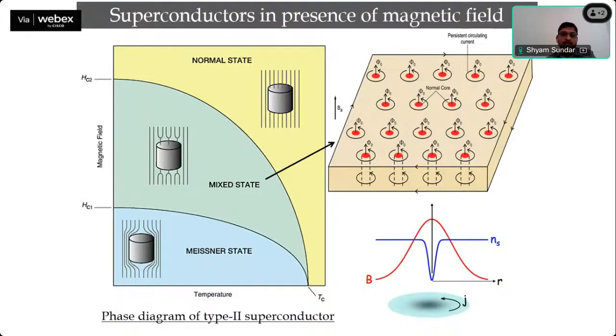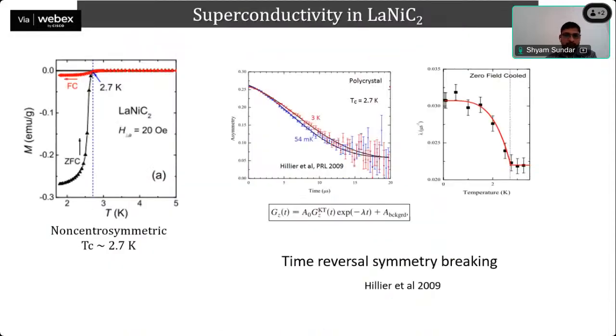So if you can get their temperature and magnetic field dependence, you can tell what the superconducting gap structure of your superconducting material is. You can tell about the pairing symmetry and so on. I studied a superconductor called LaNiC2, lanthanum nickel carbon 2, which is a non-centrosymmetric superconductor. These are very interesting materials because they can show highly exotic and unconventional superconductivity. LaNiC2 shows a superconducting transition around 2.7 Kelvin.